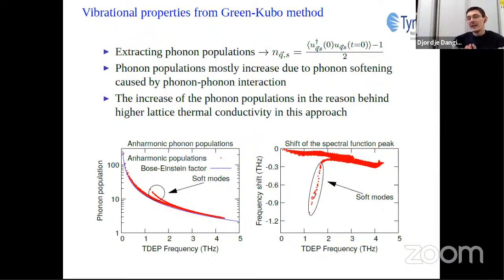So why is there an increase in the lattice thermal conductivity then in the Green-Kubo approach? We explain that by extracting the anharmonic phonon populations from the displacement autocorrelation functions. And we can see that anharmonic phonon populations mostly increase in the entire frequency range, and most prominently for the phonon soft modes. So we can say that the increase in the lattice thermal conductivity that we observe in the Green-Kubo approach is actually due to the increased phonon populations.